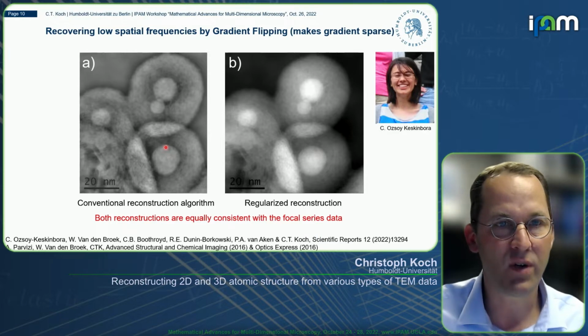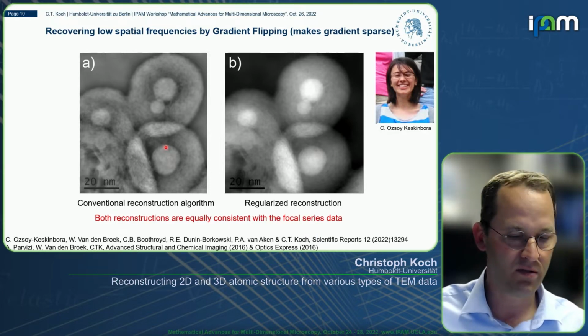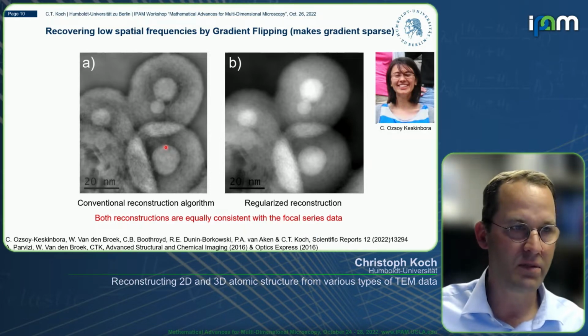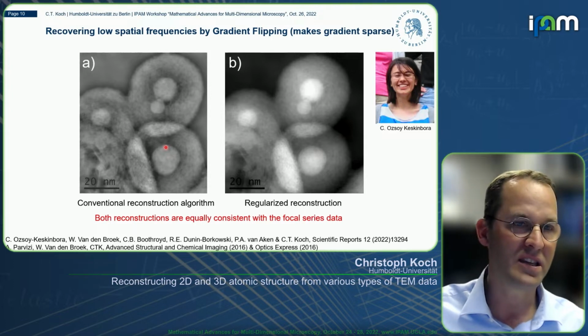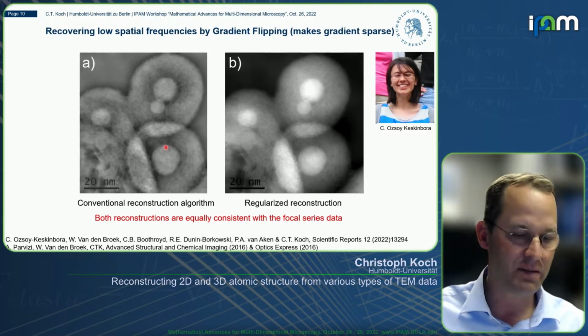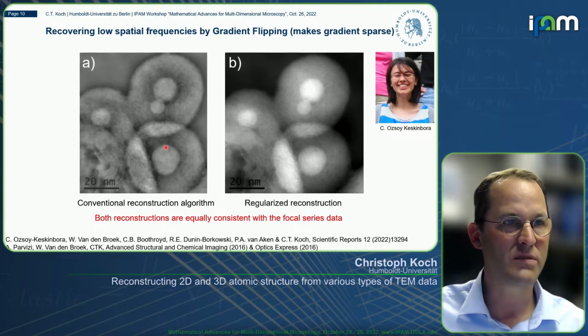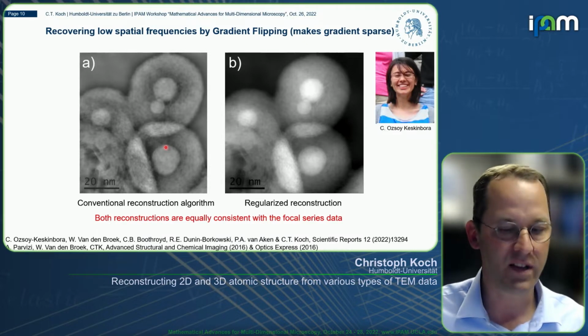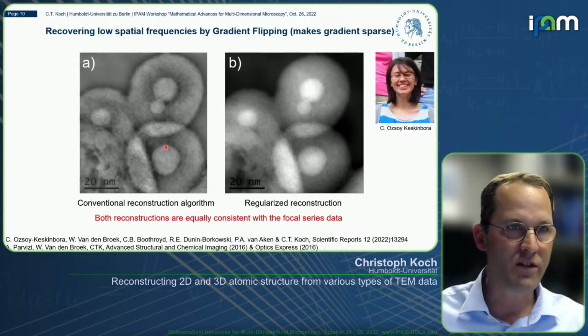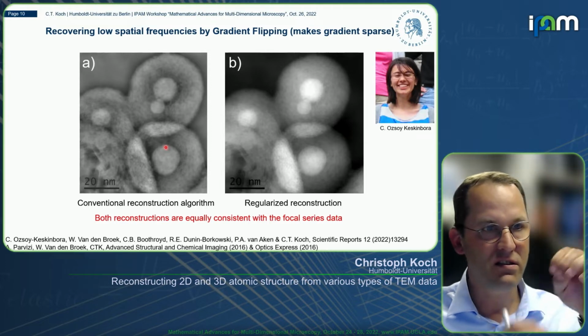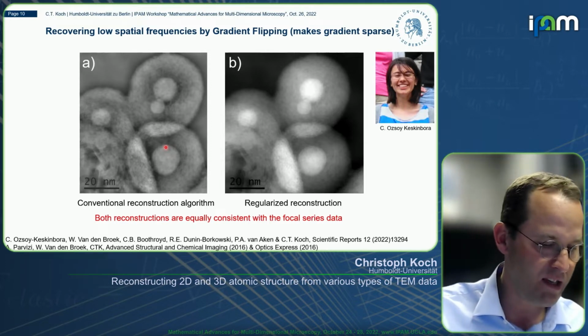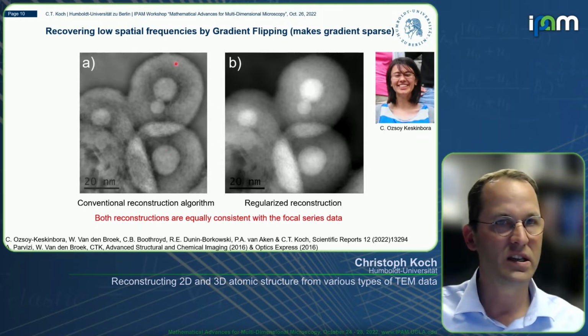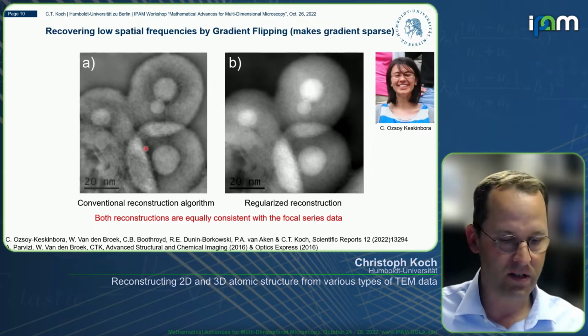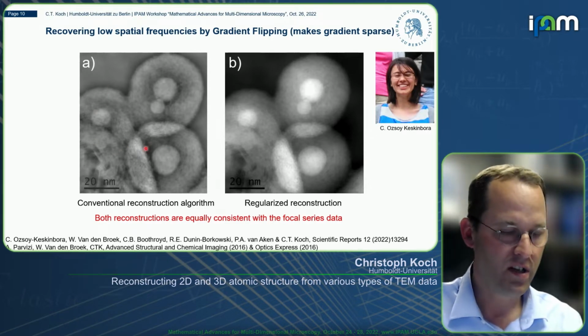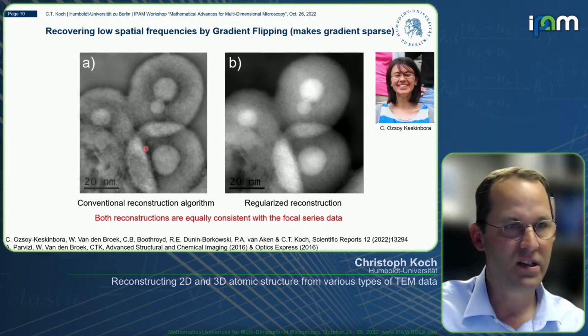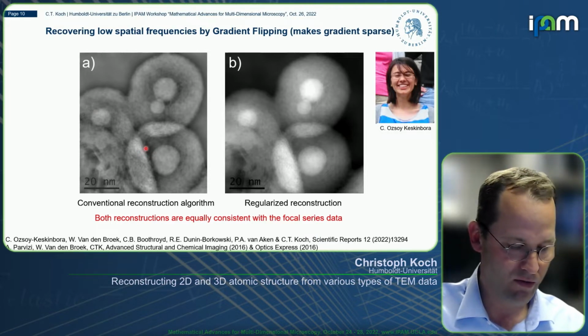It's a bit like the missing wedge, like we heard yesterday also, the missing wedge problem in tomography. There is data that you didn't acquire, and somehow you now have to make up for this missing information because it produces artifacts otherwise. In tomography, it produces these elongations along the z direction. In focus series reconstruction, it means that you have missing low spatial frequencies, which you want to recover to make your data more physically reasonable, if you like.